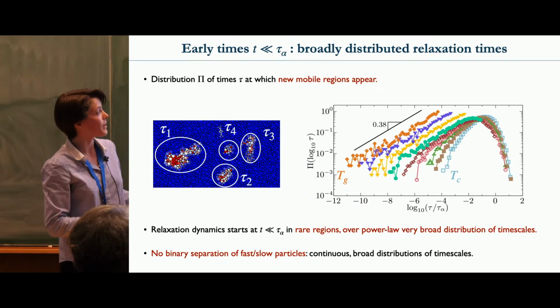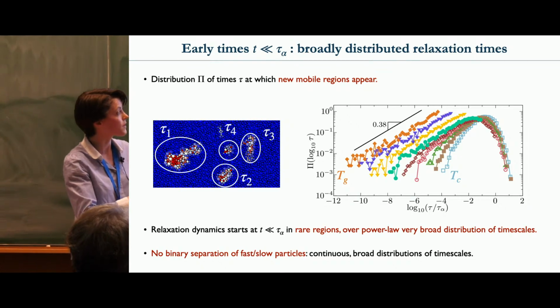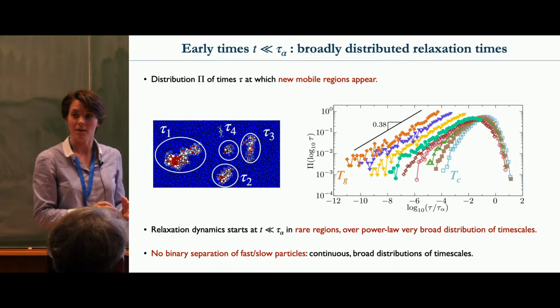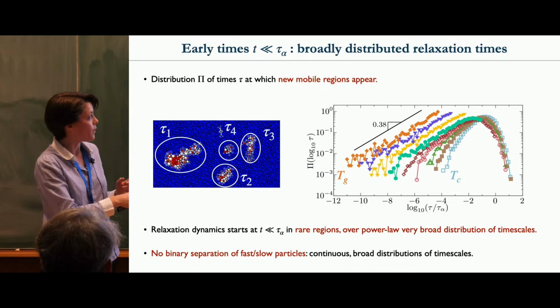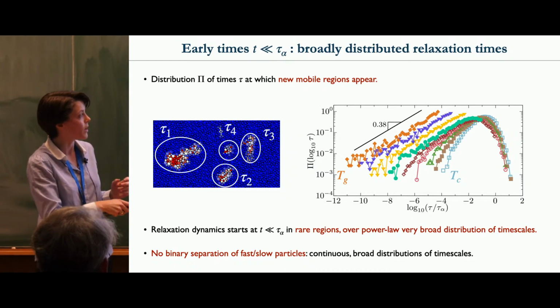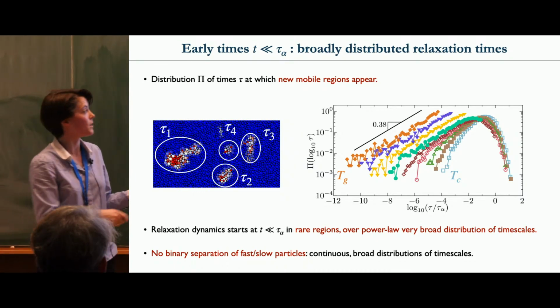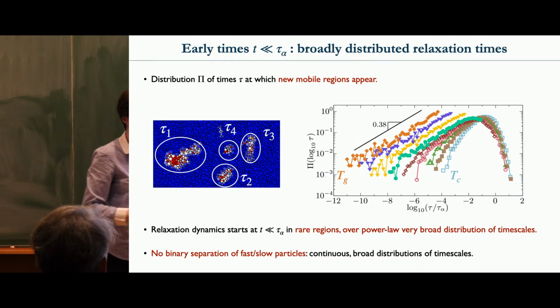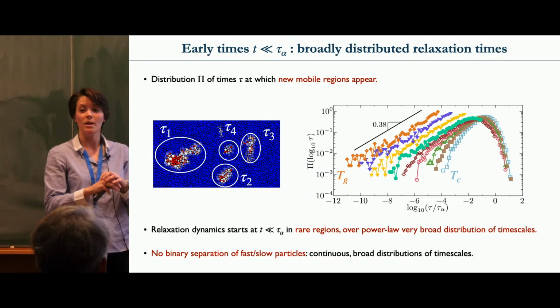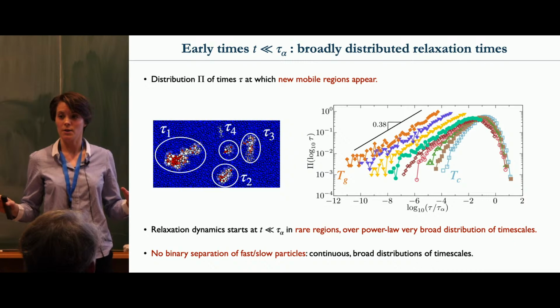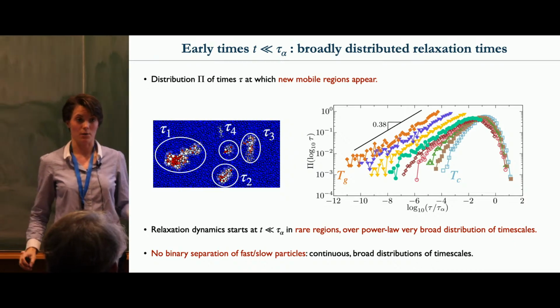The main aspect here is that the relaxation starts actually at the very start of the simulation. You have, 12 decades before the relaxation time, some mobile particles that appear. This is a continuous process indicating that there is a really broad distribution of timescales for the apparition of these clusters, not just one.